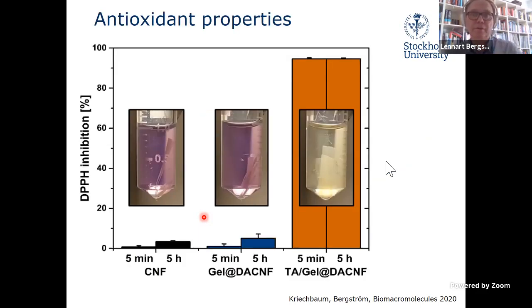The addition of tannins, like tannic acid, also imparts the material with another property: antioxidant properties. You can see that adding tannic acid means it can inhibit free radicals very strongly, over an extended period of time—not only after 5 minutes, but also after 5 hours. This could be of interest for some types of packaging materials, for example food packaging.